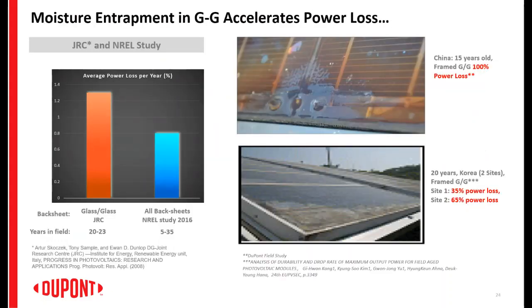In fact, the phenomenon of moisture and gas entrapment in glass modules and its impact has already been seen in old generation glass modules, and has been widely reported as well. The graph on your left-hand side shows results of studies on fielded modules done by two independent organizations. One is JRC, a research organization based in Europe, and the second is NREL, which is more well known, and is based in the USA. It shows a very high average power loss of 1.3% in old glass modules, as compared to the 0.5% that one would typically dial into their financial calculations.